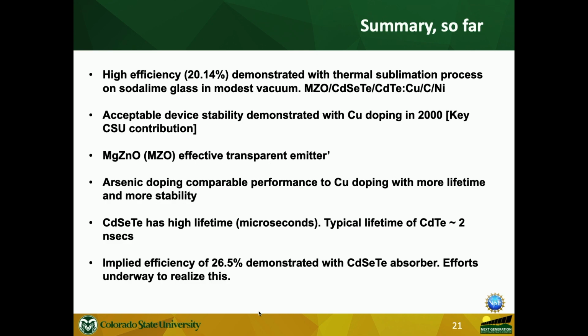And the MZO film itself evolved from our lab. The major contribution, as I see it, that led the industry to move forward was the idea that you could put copper in controlled conditions. We did this for First Solar, on their material. When the main investors were having a difficult time funding the project, when you couldn't show stability, we showed that with small amounts of copper, you can make it live acceptably. It's not great stability. With very high temperatures, you can have some problems. But if you leave it outdoors and you don't cross 65 degrees C, with mild controlled amounts of copper, you can make it work. And this is our key contribution.